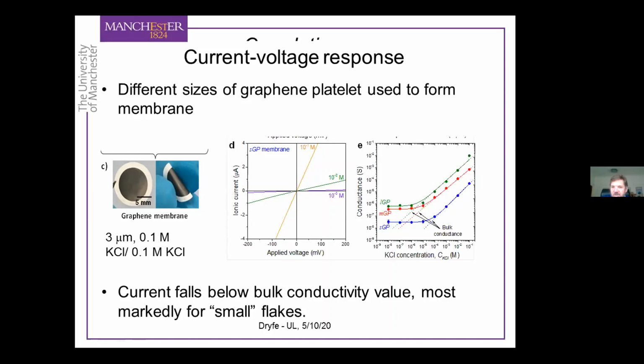And what you see at high concentrations, you can obviously measure the effective conductance of the membrane. At high concentrations, the conductance is dominated by the bulk electrolyte solution. So as you decrease the solution concentration, the conductance falls. But it falls to a minimum value because at some point, the conductance doesn't become dictated by the concentration of the electrolyte, it becomes dictated by the charge on the membrane itself. So you move from bulk controlled conductivity to surface controlled conductivity. And where you get that transition depends on the size of the platelets that are used to form the membrane. Basically, if you use smaller platelets, they have more edge, and therefore they have a higher surface charge, and therefore the transition from bulk to surface conductivity occurs at higher concentrations.